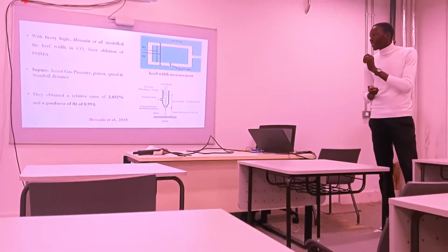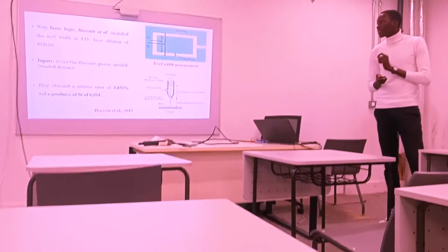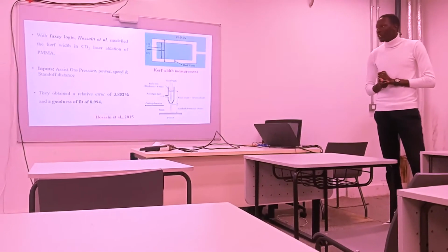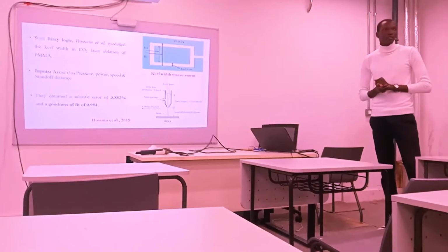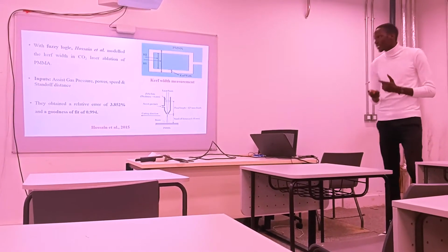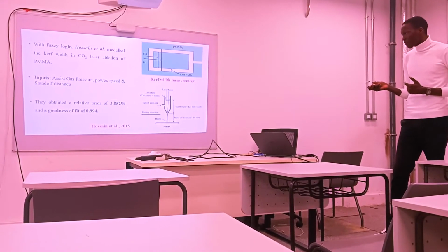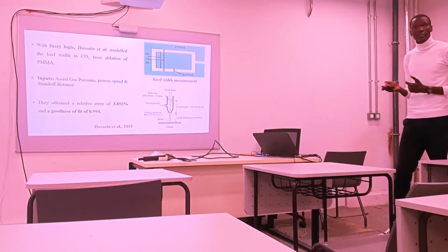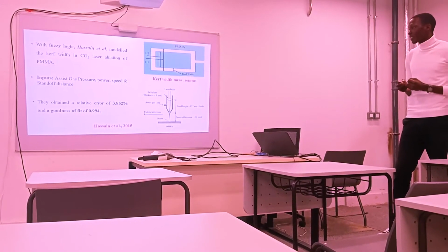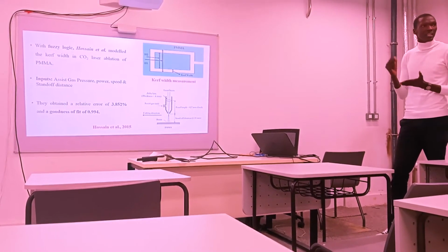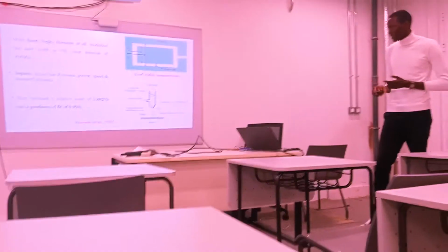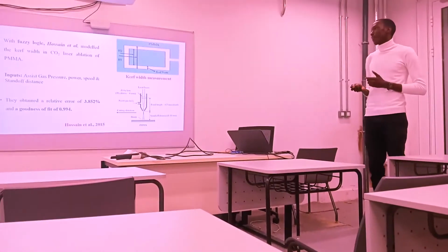And then they obtained a relative error of only 3.852% and a goodness of fit of 0.994. That shows that the results were highly accurate. This value of 3.852 is a very good result because in most cases, an error of up to 10% is acceptable. So to get something like this means they really did something good.